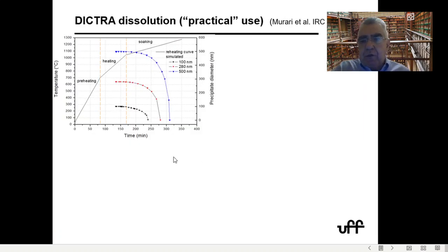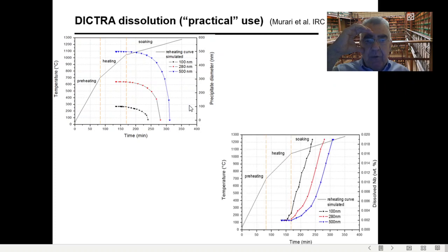Now, one way of looking at it is, if you have your heating cycle for the plate, this is an industrial heating cycle, then you can use DICTRA or a diffusion model to calculate how particles of different sizes dissolve. And then, using the same heating curve, you can calculate how much niobium, for instance, you have in solution, depending on the size of the particles. So with this information, you can get how much niobium you're going to have in solution to help you during rolling. And keep in mind that this is not happening at the equilibrium dissolution, because it takes a long time to dissolve if you're going to the equilibrium dissolution temperature. So normally you have to overshoot, you have to heat higher than just the equilibrium temperature.